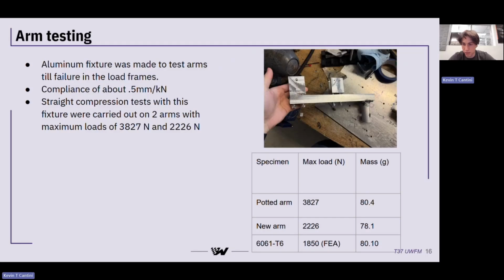Then we had to test the arms. We machined an aluminum test fixture to test these arms in the load frame. In straight compression, a potted arm carried 3,827 newtons, and a new arm that was not potted carried 2,226 newtons, well above the expected 1,850 newtons for an aluminum arm with the similar mass. So we're matching or beating aluminum in strength.